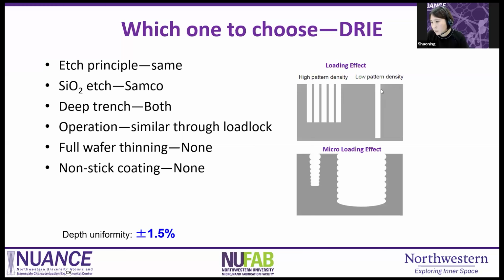So the etching result will be lower pattern density will give you a higher etching rate. So that's why we always have a range of the etching rate. Also, if you put two different opening sizes in your mask design, for example, this is 5 micron only, this is nearly 200 micrometer, on the same piece of wafer, you're going to get much slower etching in the smaller opening. So what I suggest is you even out the pattern density. Try to make the feature size closer as much as you could. And if you couldn't, try to put some dummy patterns nearby to even out the etching rate.